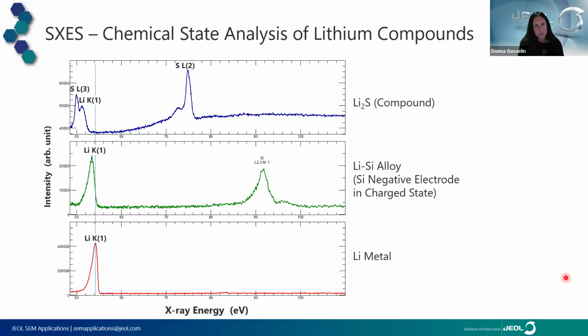Here are another couple of examples of soft X-ray spectra where you can see differences in spectrum shape. Between lithium metal and lithium sulfide here, you not only see difference in the shape, but you can also see kind of a shift in the lithium line, which is giving us some kind of indication that we're getting alloying or bonding.